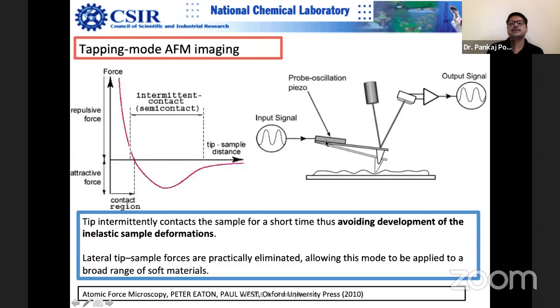And when you apply the sinusoidal voltage, what exactly happens? This piezo material will also move up and down, it will flex and it will contract. It will contract and it will expand. So there may be some phase lag from this to this, but it doesn't matter what the phase lag is, because it's already calibrated. So when this piezo moves up and down, it oscillates the cantilever also with the same frequency and the same amplitude. So for example, when you apply a certain voltage, you can control the oscillation frequency and oscillation amplitude. If you apply larger and larger voltage, the tip starts oscillating with a larger amplitude. So that's the way you can control the oscillations, amplitude and frequency.